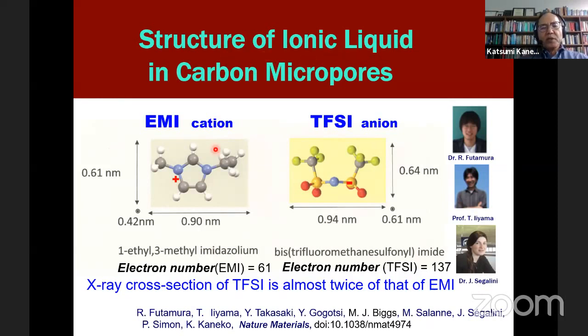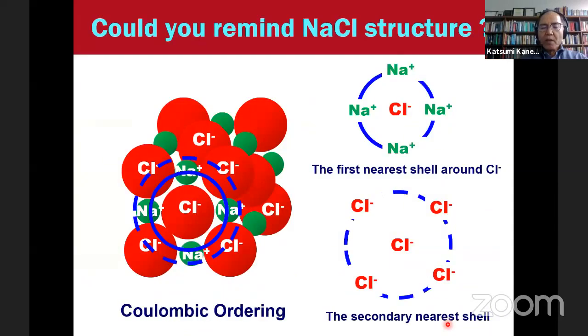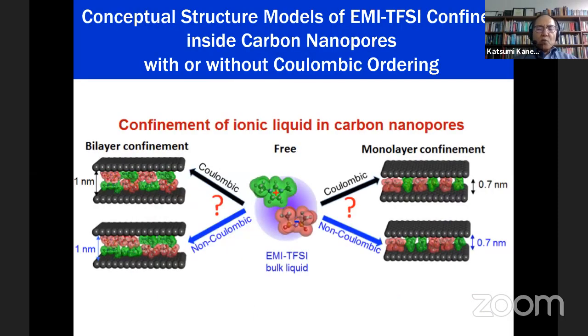We used the ionic liquid EMI TFSI. We confined it in the carbon pores. Then we measured synchrotron X-ray scattering. Then we applied hybrid reverse Monte Carlo simulations. Ordinarily, ion structure is very, very ordered. As shown here, this is NaCl: around the Cl minus anion, the first coordination cell is occupied by the sodium plus cation, and the second coordination cell is occupied by the anion. This is Coulombic ordering. We wondered whether this structure would change under strong confinement.